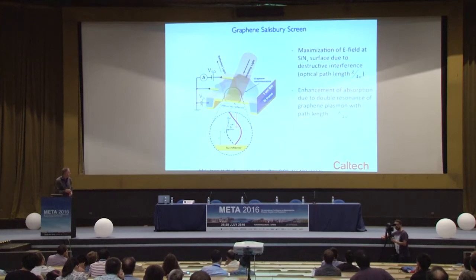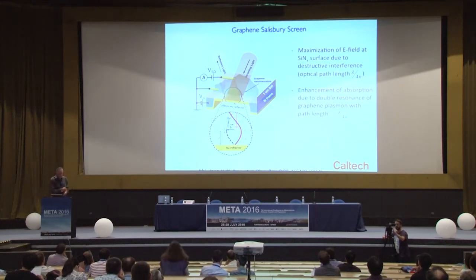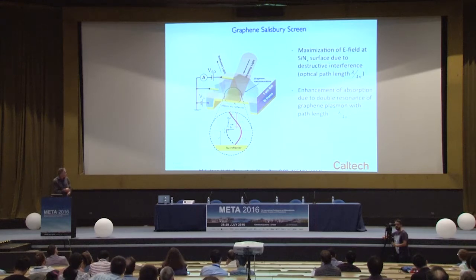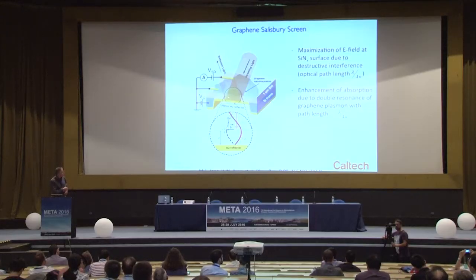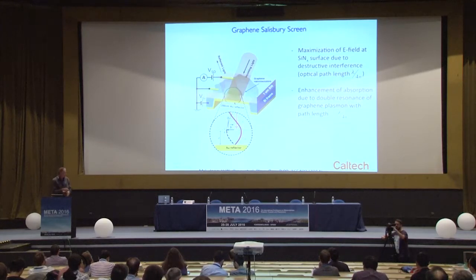To further increase the absorption and really achieve very large absorptions in graphene, we want to go to a resonant structure that was first noted by Salisbury in the microwave literature, who essentially was interested in the problem of making very high impedance surfaces. And what he recognized was that to match an extremely conducting thin sheet to free space was quite a challenge and required a resonant geometry using an interaction with a back reflector, with a thin sheet, in our case graphene, positioned a quarter of a wavelength in the index away from a back reflecting substrate.